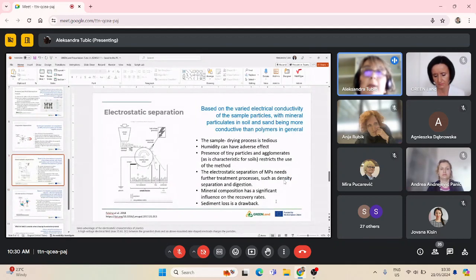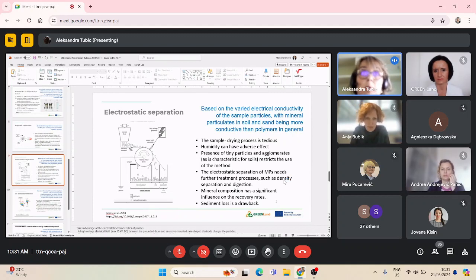Electrostatic separation also is not very widely used, but we have to mention it here. It is based on varied electrical conductivity of the sample particles, with mineral particulates in soil and sand being more conductive than polymers in general. The sample drying process is tedious. Humidity can have an adverse effect. Tiny particles and agglomerates can also have an adverse effect on this method. Electrostatic separation of microplastics needs further treatment, such as density separation or digestion, but still has found its place in some research papers. Mineral composition also has a significant influence, and one of the drawbacks is sediment loss.